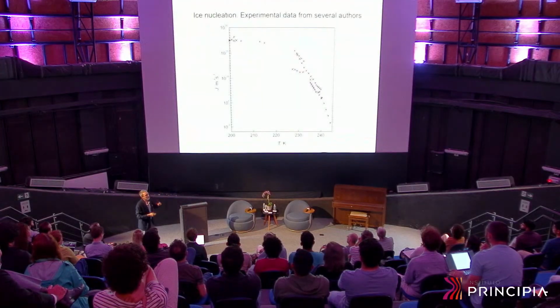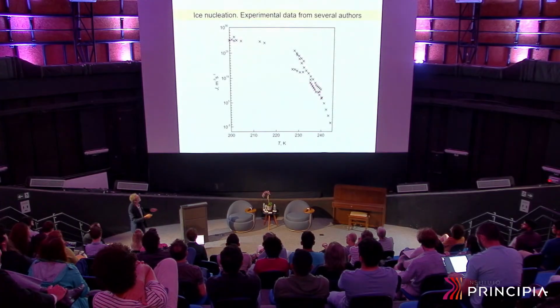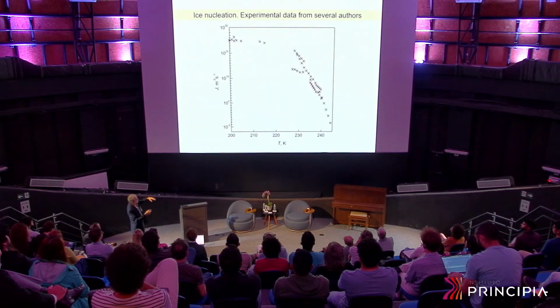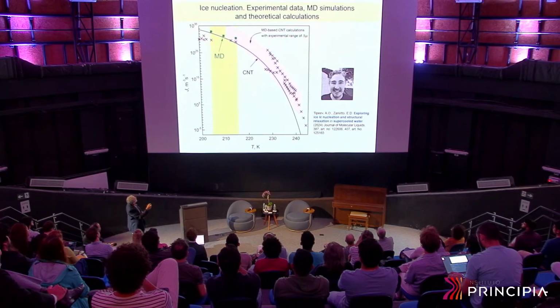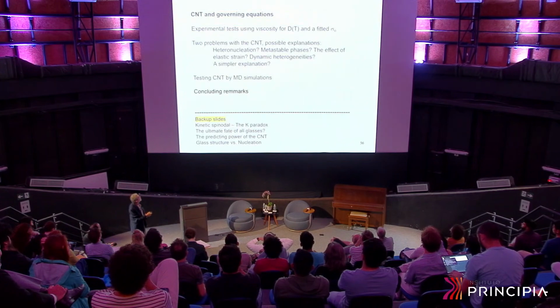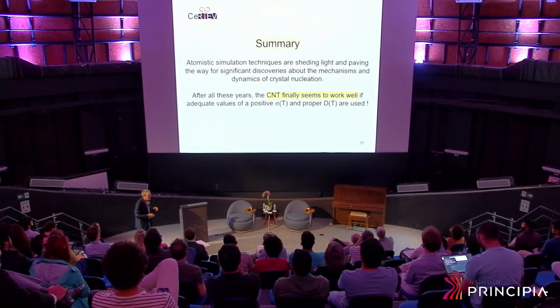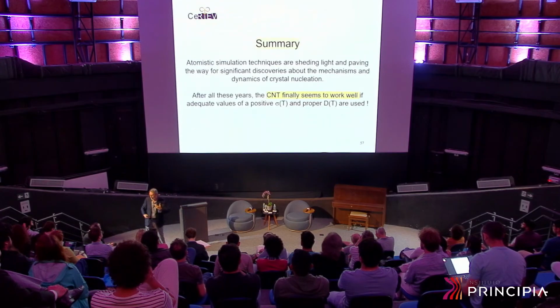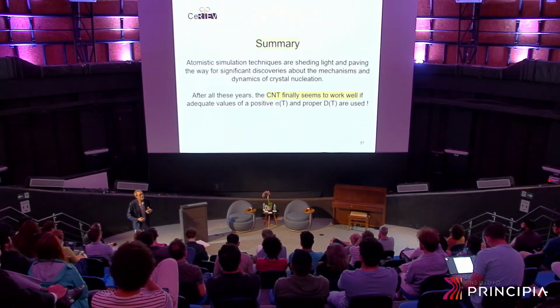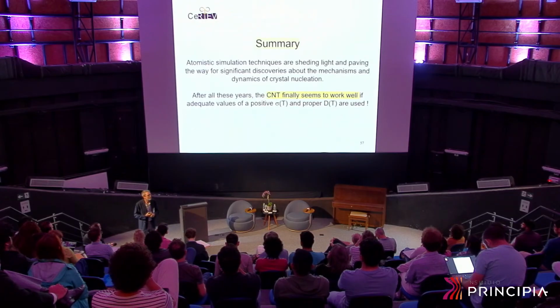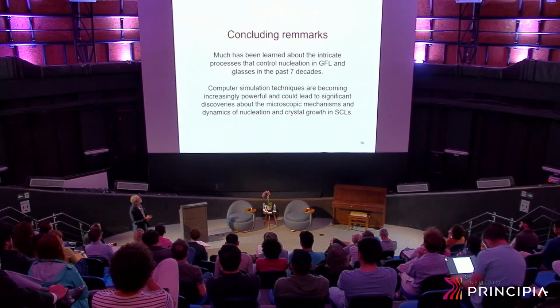Anyway, many people have measured nucleation rates in water because this is the most important liquid for us. Experimental data from different authors, and then our MD simulations, this is with ICTP-SAIFR, and predictions of the classical nucleation theory for water. So with that, I finish saying that the combination of experimental years of work with MD simulations performed during the pandemic years shed light on this very old and complicated problem, which is so important for metallurgy, for mineral formation, for glass ceramics. Crystallization is a very important phenomenon in nature anyway.